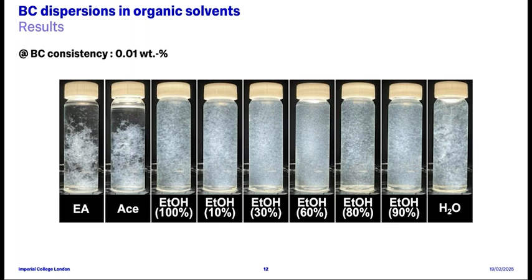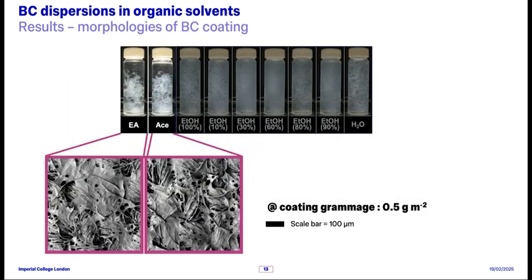Agglomeration can be easily observed in the ethyl acetate and acetone suspensions because of the solvophobicity of bacterial cellulose in these 2 solvents. And a more homogeneous suspension can be observed when ethanol-water mixture or water is used as the dispersing media. And the coverage of bacterial cellulose nanofibers with a coating grammage of 0.5 gram per square meter is also shown here. And consistent with what we observed earlier, the agglomeration of bacterial cellulose dispersed in both ethyl acetate and acetone results in a very poor bacterial cellulose coverage of the underlying fabric substrate, where we are still seeing bare and uncoated yarns, and the pore opening between the yarns remains open.